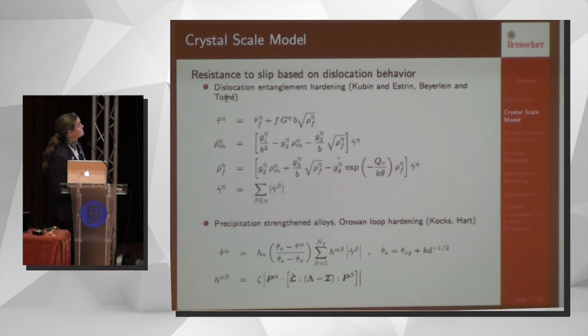So our resistance to slip, tau hat, has some friction component, which we assume is fixed, plus some evolving component that's related to the forest dislocation density rho f, that being associated with obstacle spacing. And then we have evolution equations for our mobile and our forest dislocations. For the mobile dislocation equation, the first term is a constant source term. The second and third terms are minuses. The second term is when a mobile dislocation is immobilized by running into another mobile dislocation, so when a mobile traps a mobile. And the last term there is when a forest dislocation traps a mobile.